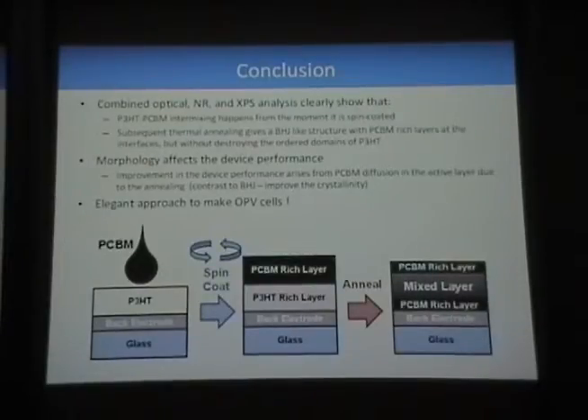So, just to summarise, when you spin coat, you end up with a PCBM rich layer on the top and a P3HT rich layer on the bottom. And the subsequent annealing process gives you a BHJ-like layer with a PCBM rich layer at the interfaces, but a mixed layer, which still maintains the ordered domains of the P3HT. Also, I showed to you today that the morphology clearly affects the device performance.